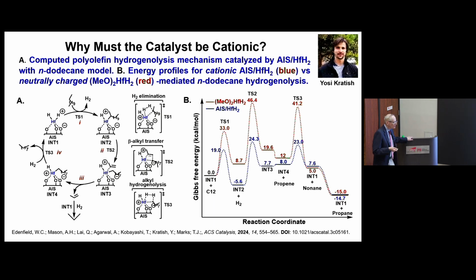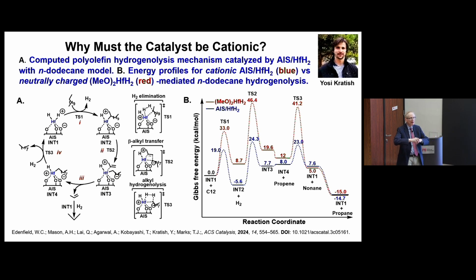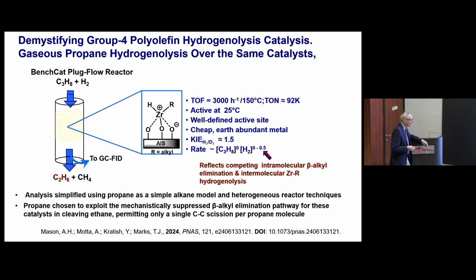Now, let me go one step further in terms of the mechanism. And that is, a purist would say, wait a minute, you've got this supported catalyst all swimming around in this big glob of goo of the polymer. How can you really understand the details of the mechanism? So we're going to use a model polyolefin, propane, and this is a heterogeneous reactor. It's a BenchCat made by Altamira. So it's an automated system where you can automatically program the temperature, the flow rate, and everything like that. And what you see here is we duplicate what we see in the big mix of polymer, but we can get the kinetics out, and now we really know what's going on here.